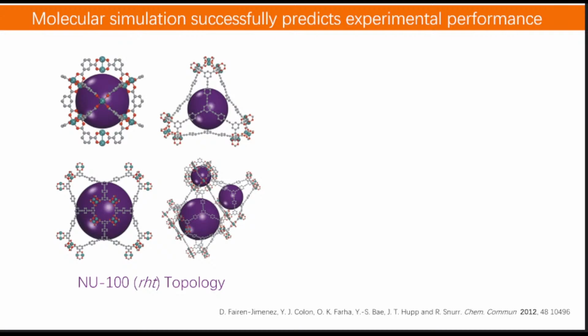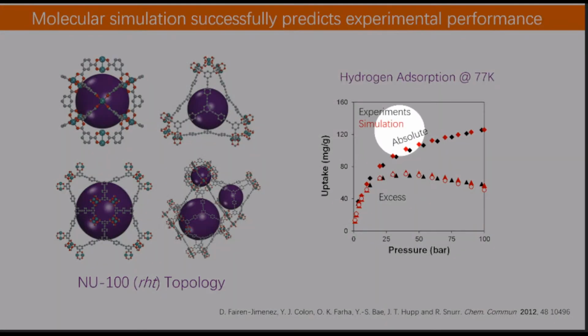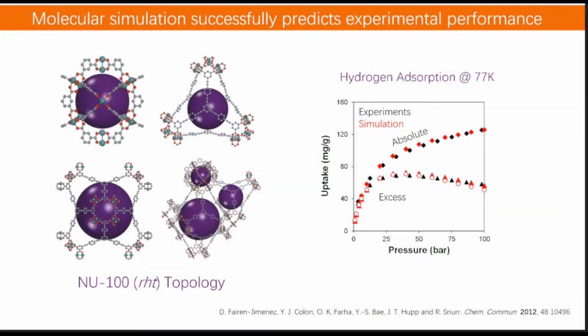So using molecular simulation, we can focus on hydrogen absorption at 77 Kelvin. It's interesting for energy applications. I have here the uptake of hydrogen, in milligrams of hydrogen per gram of sample, when I increase the pressure. And you can see here the isotherms, the experimental one and the simulated ones. And you can see a really nice match with the experimental data when we were running these simulations.